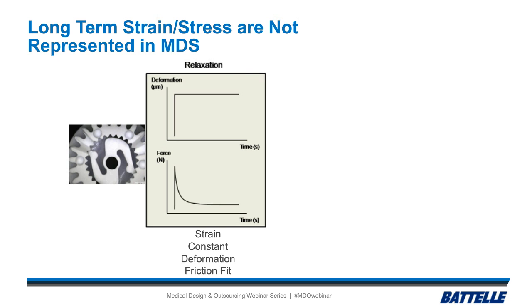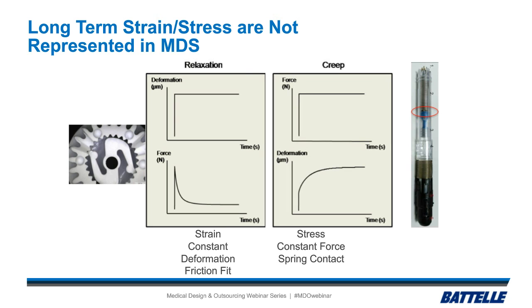The second one is creep. So creep is another long-term function of polymers, and this one is a constant force. So think of the spring that's up against that blue piece of plastic on the right. It's putting a constant force on there, and then that blue piece is constantly deforming. So the deformation gets more and more over time, but that spring is still pressing on it, so you have nearly a constant force as it extends a little bit. And you could get deformation of parts to the point where they don't fit or interact well with the parts around them or don't function as they're supposed to if they're deformed. So that's the downside of long-term creep.